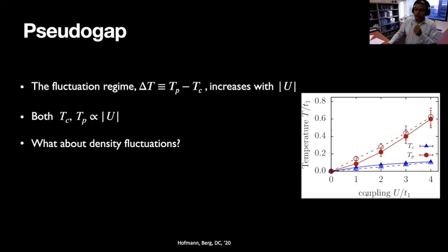Okay, and the higher up you go in your strength of interactions, the wider this regime is, where the system is very incoherent. We also looked at some proxies for the spectral functions, which I'm not going to show you here. I'm happy to do that later. Basically, if you ask whether or not there is any sign of a Fermi surface or something, then the answer is no. This looks completely incoherent in momentum space. Okay, so unlike the previous example for the square lattice Hubbard model, where this pairing scale was still proportional to U, but the phase stiffness started going as t squared over U.